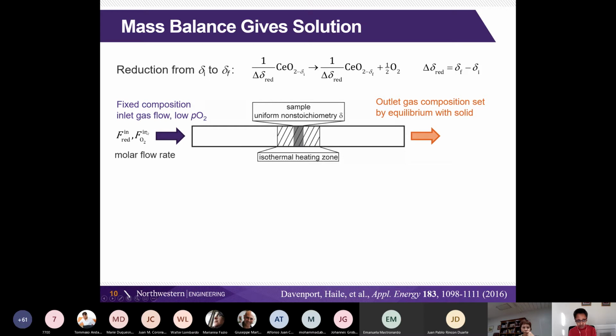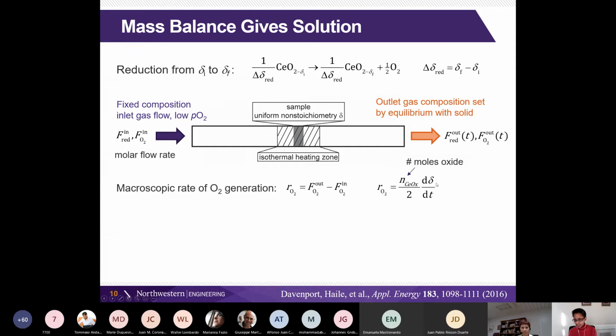What we're saying is that we are controlling the flow rate of the gas coming in. We have a total flow rate of that reducing gas, and we know exactly what the oxygen content is in that reducing gas. What comes out is a total flow rate of gas, and its amount changes with time, and some fraction of it is the oxygen coming out, which is also changing with time. So these are the things that we'd like to know. Well, the macroscopic rate of oxygen generation should just be the difference between what was coming in and what's coming out in terms of oxygen.